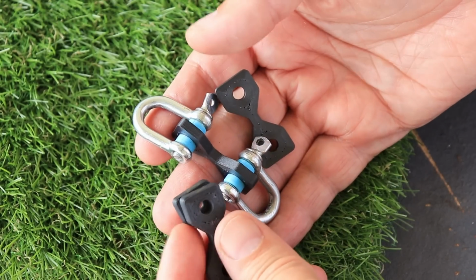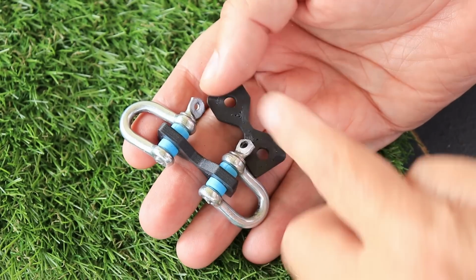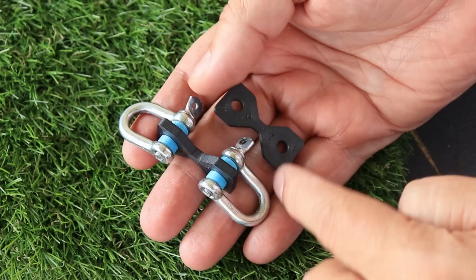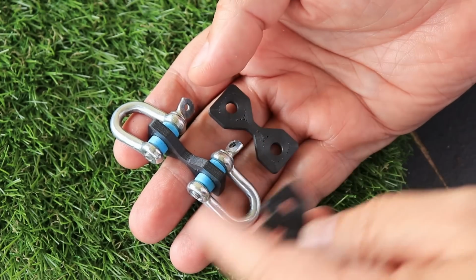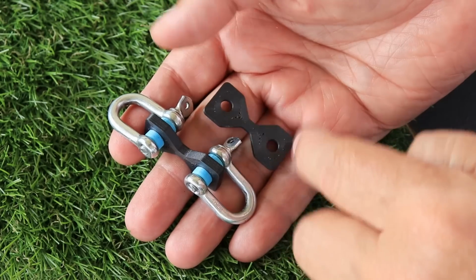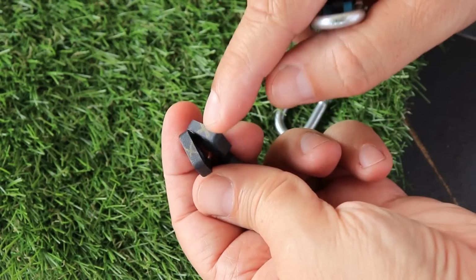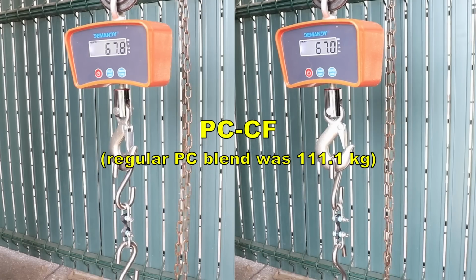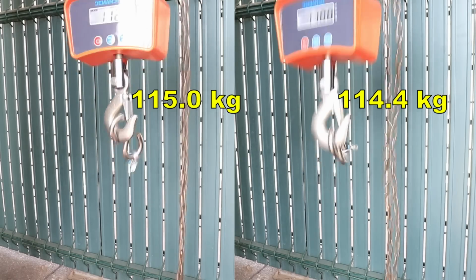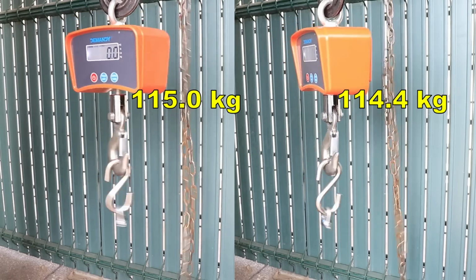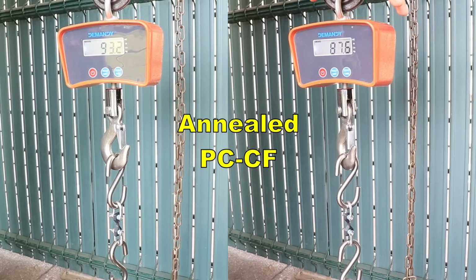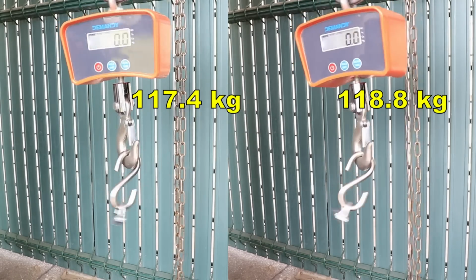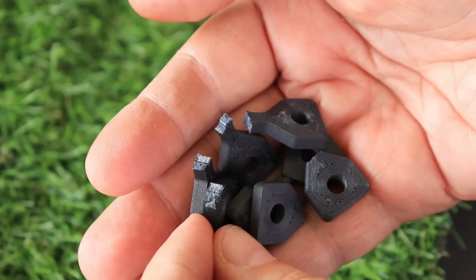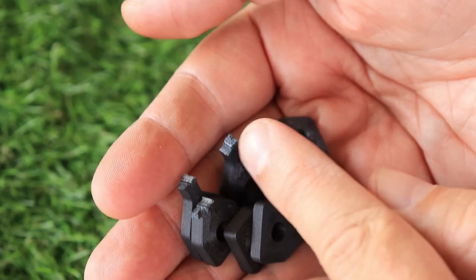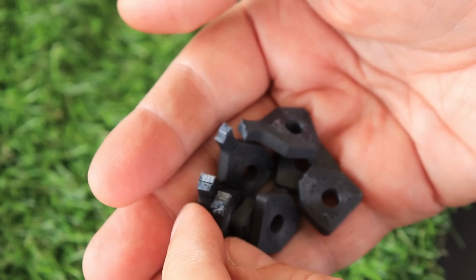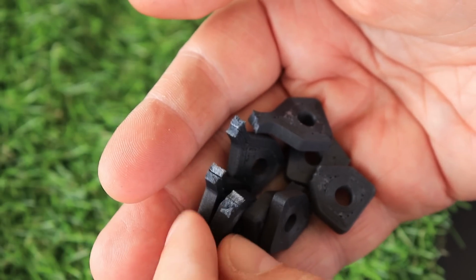And now let's start with the mechanical testing. I'm starting with tensile strength. These test objects are printed in horizontal position, and the smallest cross-section area is 4x4 millimeters. And I'm starting with regular carbon fiber PC blend, and then with the annealed version. Well, for the feeling it was okay, strong, but when I see this kind of cross-section areas, these are signs of weaker layer adhesion, but I will find that out in a few minutes.